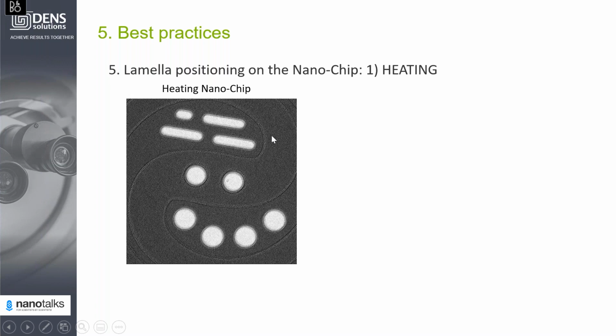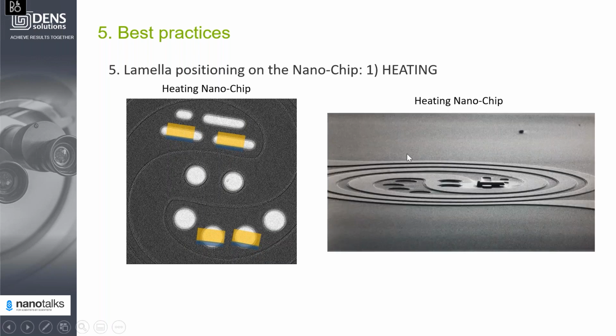So how do you put the sample lamella on the heating chip? This is the top view of a heating chip. Here you see the heating line. This is our silicon nitride and the windows. In this geometry, you would put the lamella here on the windows, to have a bit more distance from the lamella to the heating lines, not to damage them during the milling process. This is a side view from an SEM image. So basically the lamella is prepared on one of the elongated oval shape windows.